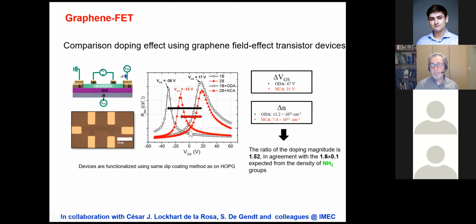But then we teamed up with our colleagues at IMEC, which is a Nanoelectronics Institute in Leuven, and we looked into the impact of exposing graphene field effect transistors to a monolayer or even multilayers of this type of molecules. And it was pleasing to see that the transfer curves, and the degree of doping that we can extract from this data, scale very well with the density of the amino groups on the surface. Actually, we can restore the properties of the pristine graphene by just washing away these molecular physisorbed systems.